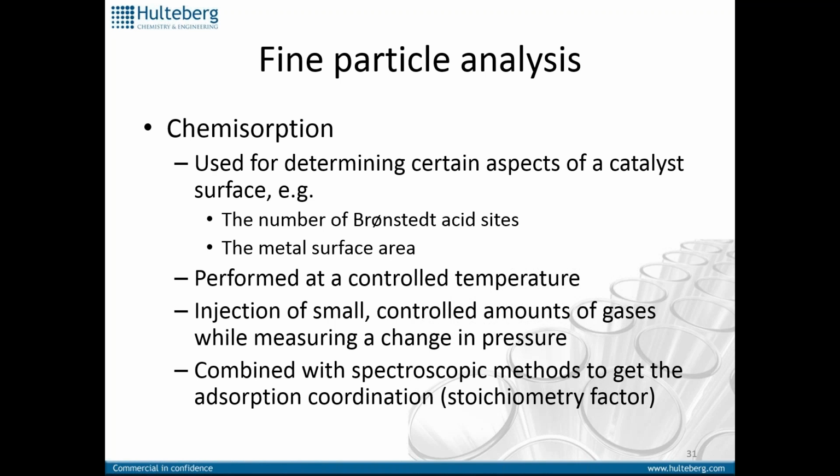In this case, however, we will get a reaction with the material, and we'll first do one analysis, and then we will redo the analysis immediately thereafter on the same material to be able to differentiate the chemisorbed and physisorbed material, and then the difference should be a straight line between those two and give us the volume of chemisorbed material.